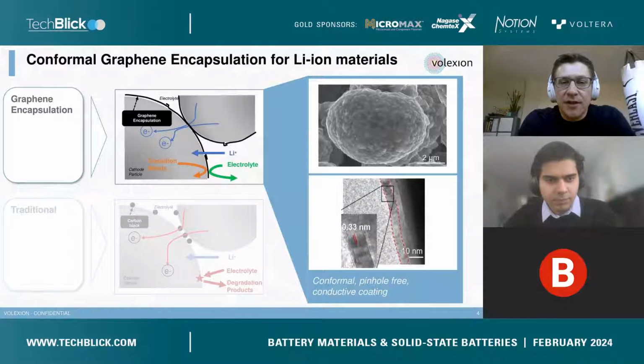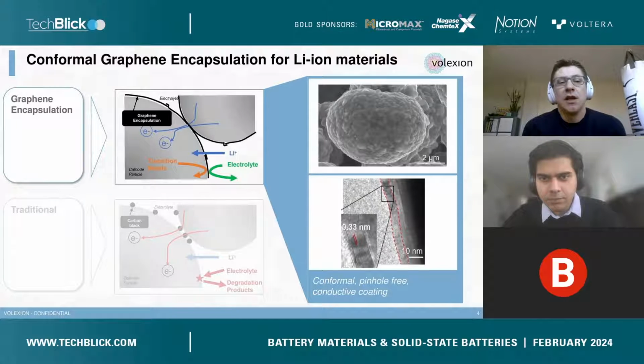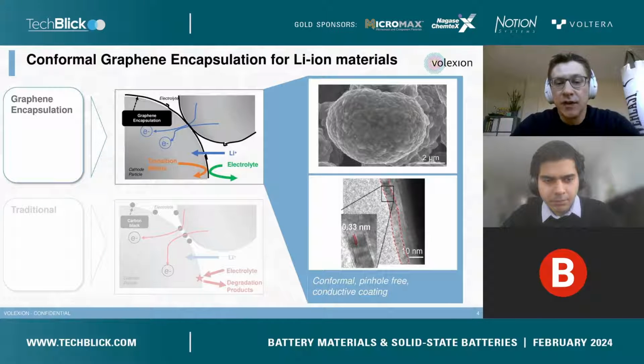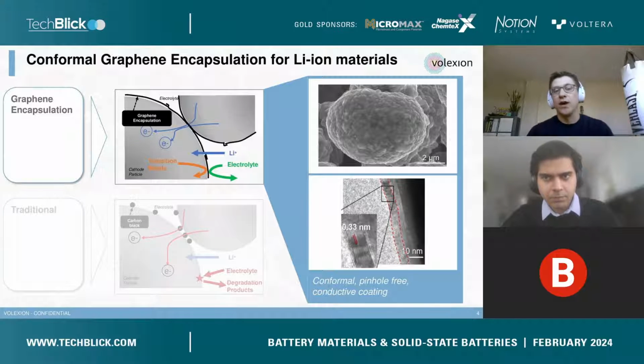What we do here can be seen on the top right image, which is an SEM image of an NCA particle. NCA is one of the nickel-rich chemistries that's commonly used in the industry. We don't make the NCA base material at Volexion, but we make the graphene-based encapsulation that you can see on the bottom right image. That's made of few-layered pristine graphene, for which we have developed technology in collaboration with Northwestern University and Argonne National Laboratory to deploy a nanoscale, continuous, pinhole-free coating that we can deploy across a variety of substrates. And in our case, it's cathode material.